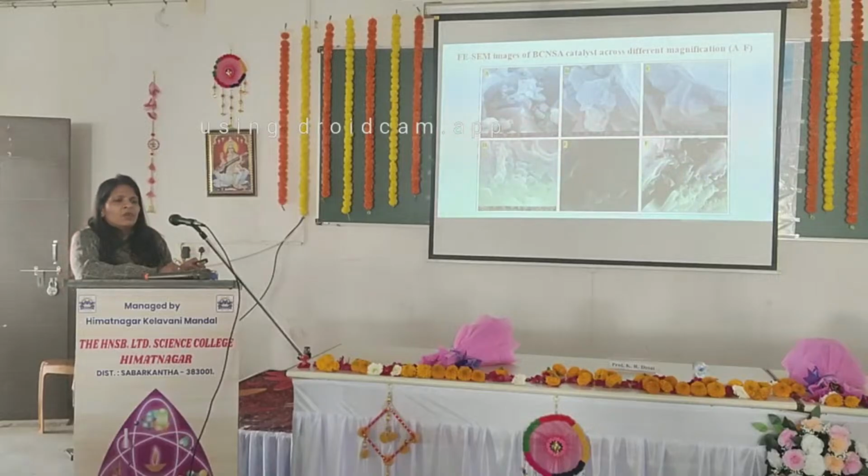Further, SEM images were taken to check the porosity and the layered morphology of the material. The EDX mapping and EDX studies were done to confirm the constitution of this catalyst, and it was found that carbon, nitrogen, oxygen and sulfur are present in different percentages, confirming the presence of these elements in our material.